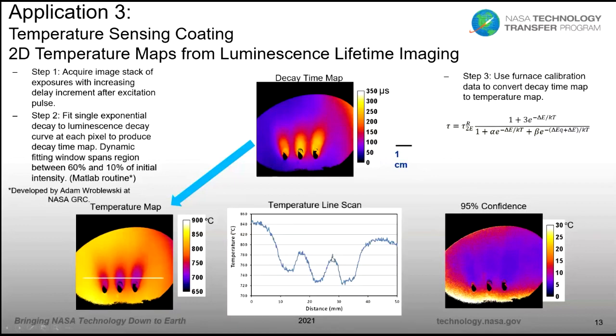You can get a better idea of the resolution by looking at a line scan across the surface where you have these cooling jets. Here you can see the coolest part is over 100 degrees C cooler than the uncooled region. But if you look at the signal to noise in here, I would maintain that we can see temperature differences on the order of 5 degrees C over distances less than a millimeter. Now, a very important product of our analysis is that we also generate a 95% confidence map, paired with each temperature map. This map contains all the error bars for the temperature readings. So if you go into one of the cooled areas here, you see the confidence interval is about plus or minus 2.5 degrees C.